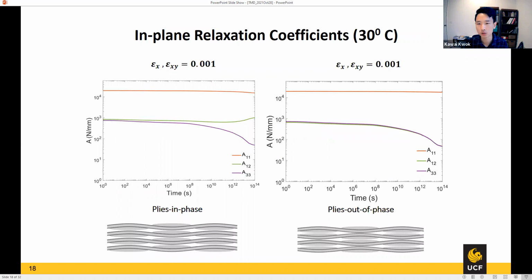So we went ahead and looked at this composite, and there was some funky behavior, as we found out along the way. On the left-hand side, we are plotting the in-plane relaxation, so we were just stretching, and we're expecting all of these relaxations to go down, right? Relaxation is always, the stiffness always goes down over time. That's why we call it relaxation. If we apply in-plane stretching of the composite, then the stiffness should go down.